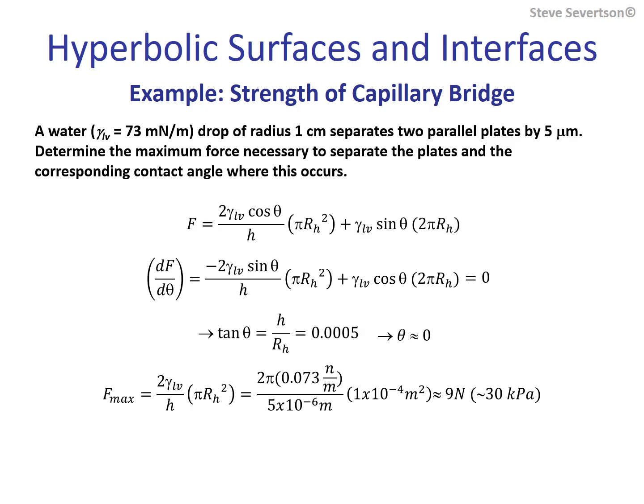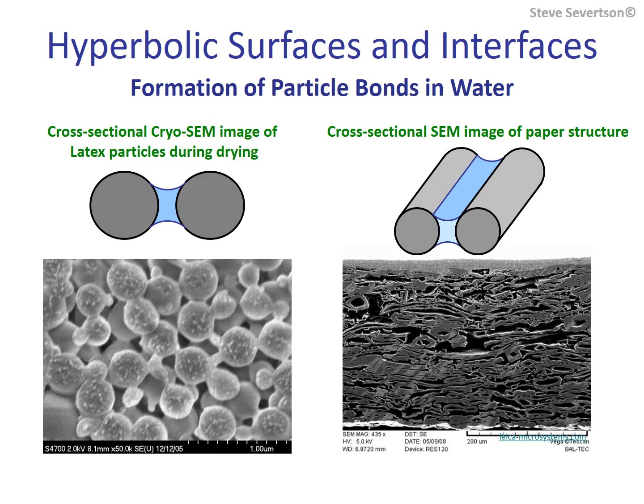The climb in compressive forces as water is evaporated is utilized to produce a wide variety of commercial products. Images show capillary bridges formed between latex particles and paper-making fibers. For latex particles, the capillary forces induce not only bonding but also the sintering of polymer particles to form structures that can be roughly described as continuous films. For paper-making fibers, strong compressive forces induced during drying due to the capillary bridge effect allow strong hydrogen bonds to form, producing a strong sheet of bonded fibers.